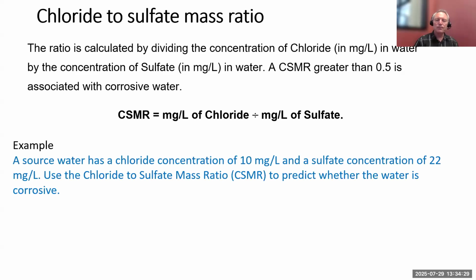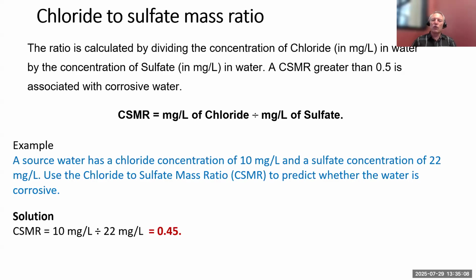And here's an example here. We have a source water and it has a chloride concentration of 10 milligrams per liter, and it has a sulfate concentration of 22 milligrams per liter. We'd obviously get this with water quality testing from a lab. And then we can use the chloride to sulfate mass ratio formula to predict whether the water is corrosive. And so here it is. We have our CSMR, 10 milligrams per liter of chloride divided by 22 milligrams per liter of sulfate. And that gives us a factor of 0.45. Let me know in the chat, is this water corrosive or non-corrosive? What do you say?